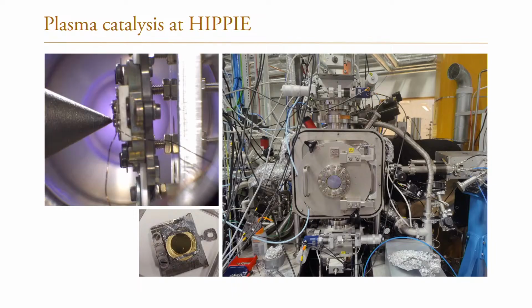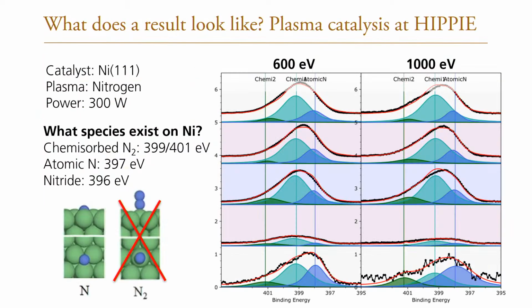This is a closer look at the sample, what it looks like. The cone is where we collect all the electrons. That, as I said, is the fingerprint of the catalyst. And also, we get very close to the catalyst, where it's directed. And then what we measure, as I said, is spectra. We have to interpret these spectra, and that's what we do maybe several months after we get back from MAX 4. We have to try to understand, what do these spectra mean?